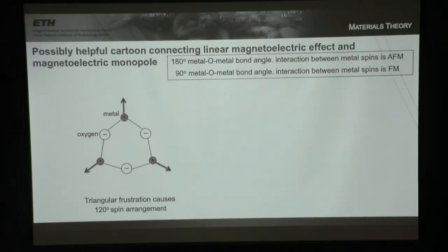I know in chemistry we learn them quite early on, but all you have to know is when I have a transition metal, oxygen, transition metal bond angle that's 180 degrees, the interaction between the spins on the transition metals is antiferromagnetic. They want to point anti-parallel. But when it's 90 degrees, this interaction is ferromagnetic. So here I've got almost 180 degree transition metal, oxygen, transition metal. These want to be antiferromagnetic. I've put them in a triangle so they can't all be antiferromagnetic to each other, just geometrically. And so they go to be 120 degrees.